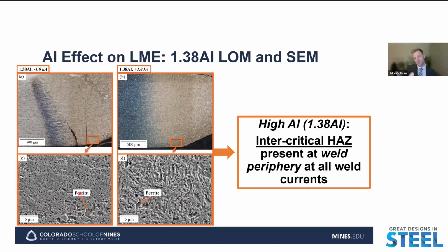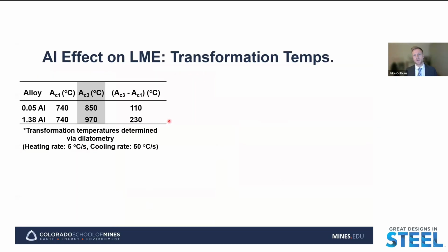And so at the peak temperature of the weld, we would expect that potentially this region was austenite plus ferrite as well, and that there wasn't full austenitization of this region at the peak temperature, and so that ferrite remains stable upon quenching. And so as we take a look at the transformation temperatures, we see that this trend begins